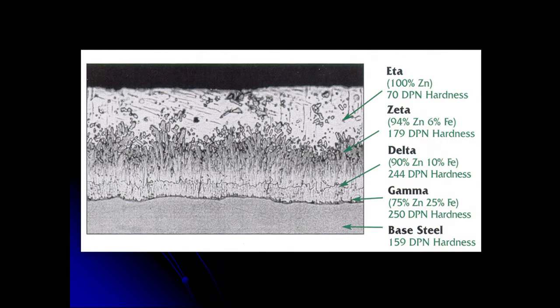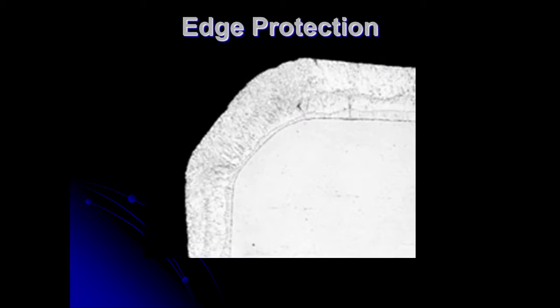Take a look at the hardness of hot-dip galvanizing. The diamond pyramid number of steel is 159 DPN. The hardness of the gamma is 250, the delta is 244, and the zeta is 179. So the first three coatings of something that's galvanized are actually harder than the steel itself. The eta is 70, it's soft, so you might dent it. That's why I can take pieces of galvanized steel and beat on these, even on the sharp edge, and it's not going to pop or peel off.